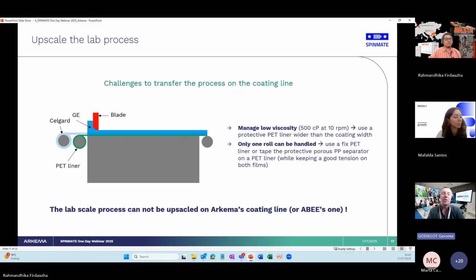And regarding the second option of having a fixed PET liner, it was not possible either, because here you can see a very simplified scheme of the process, but actually we have some intermediate rolls to maintain the film or the collector or the liner you are using, and you cannot put a fixed PET on this. So both solutions were not possible. The process developed just before is not upscalable on our coating line and on most coating lines. That's why we had to think about a new process and therefore a new formulation. So this is the next slide, please.